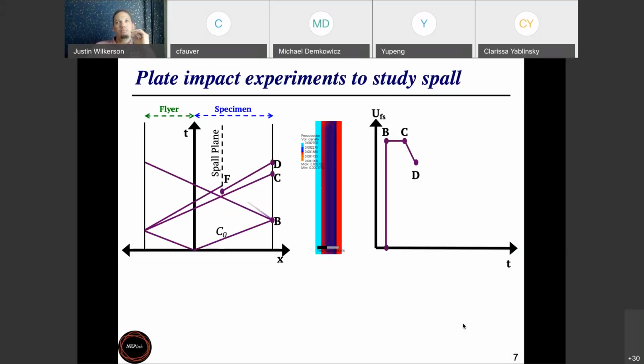So the way that nonlinear elasticity, basically the nonlinear bulk modulus of materials, dictates whether a wave will sharpen up or whether a wave will spread out. What happens in most materials, maybe all materials essentially, is that as you compress them, you are bringing the atoms closer to one another, and that tends to make the material stiffer. So you take a metal and you compress it down, and it gets stiffer and stiffer and stiffer, and it becomes harder and harder to compress the material anymore. I think you guys had a seminar on this earlier in the summer where there's a maximum compression rate that you can apply to the material, regardless of the pressure that you apply.